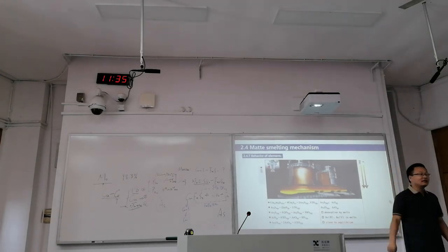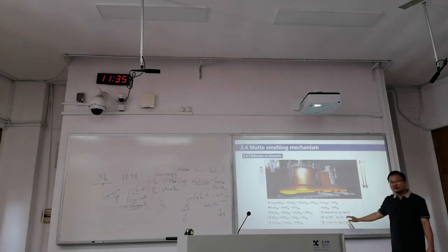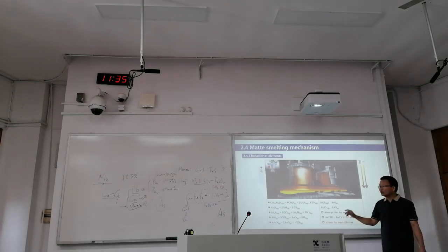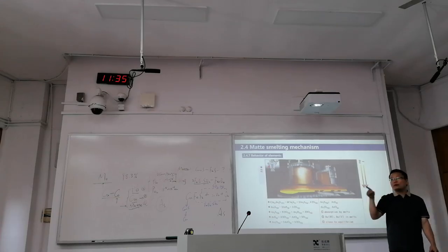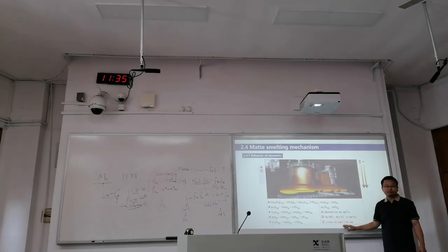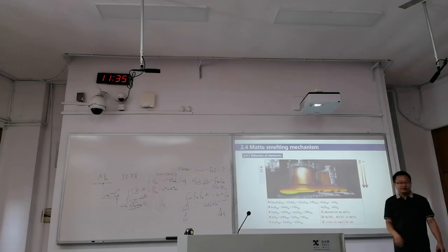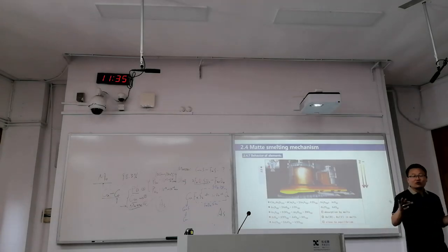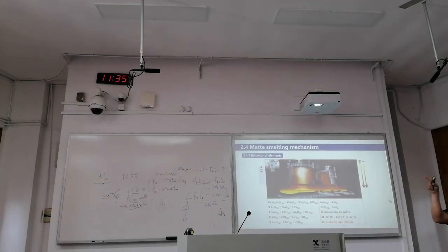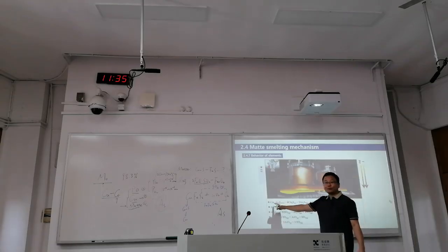So the arsenic-containing gases will penetrate into our slag and the matte, so it will be very close to equilibrium. Because for the slag, it is oxides, and oxides go to oxides. And for the matte phase, arsenic is very close with copper.